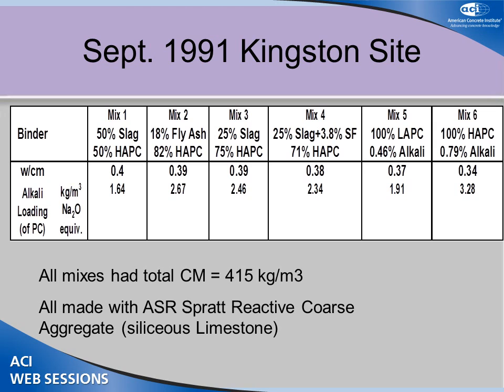We had a low-alkali Portland cement, about 0.46 alkali, to look at the low-alkali control, and then we used a straight high-alkali cement, which was about 0.8 alkali, so it wasn't super high as compared to some of the Ontario mixes. They all had a high cement content, 415, which I think is about 700 pounds per cubic yard, somewhere in that range.